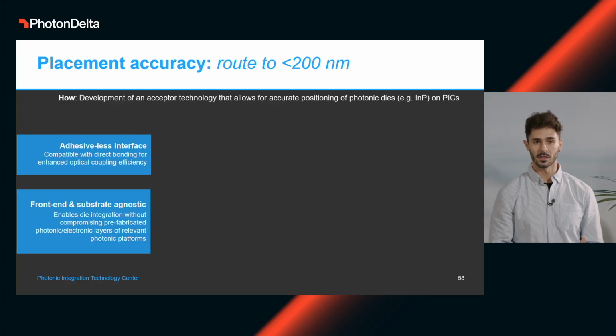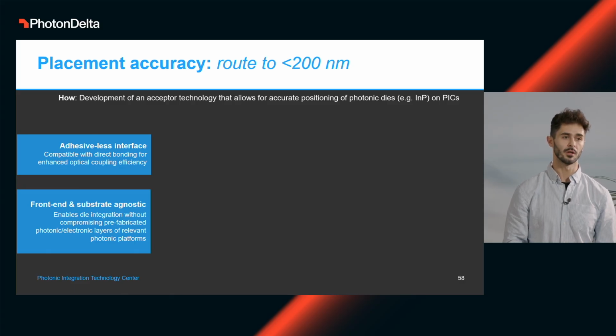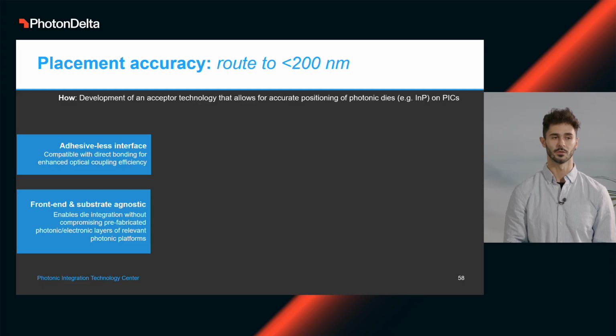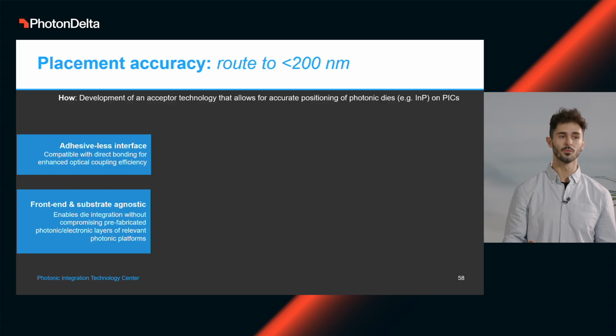Of course, accuracy is the other key challenge. We developed an acceptor technology that works in combination, and is part of our process, that allows you to create an adhesive-less interface, meaning that when the component is integrated, it doesn't need an optical adhesive to be bonded to the receiver, and is in effect connected via direct bonding to the surface. Our acceptor technology is also designed to work with most of the relevant photonics platforms. As a matter of fact, we haven't found one that doesn't work yet. And it doesn't compromise any prefabricated photonic or electronic structure that you put on.